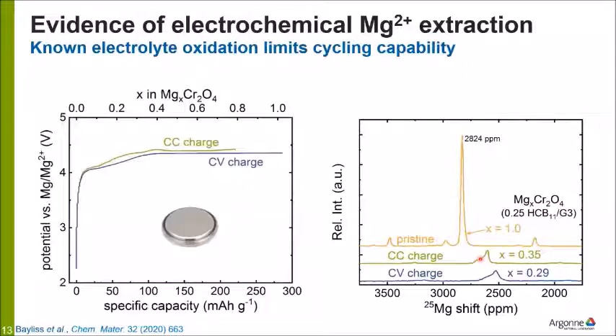There's no evidence of it going into the octahedral sites, and so this is used as data to prove that yes, indeed, the magnesium was extracted from the chromite at these very aggressive conditions. Unfortunately, due to these conditions, the evidence of reinserting magnesium was harder to come by.